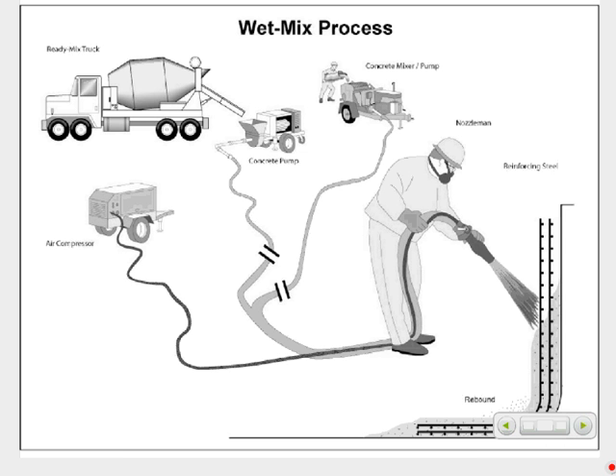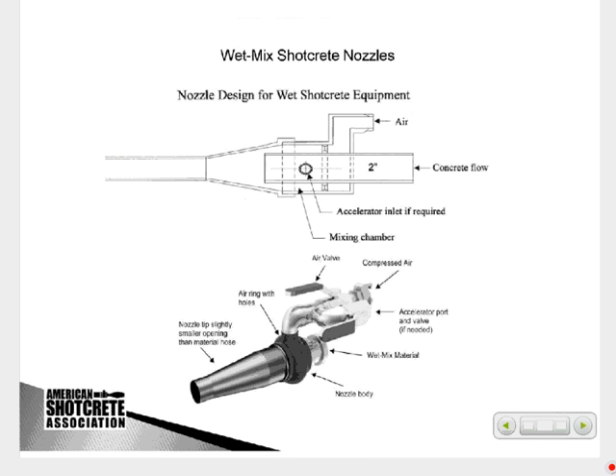It's often delivered in a concrete truck to the pump where it's then pushed with hydraulic cylinders. The swing tube type hydraulic pumps are the most common in wet mix. And then if you've ever seen a concrete pump in operation, you know you're not getting high velocity out the end of the hose. And that's why we have to introduce the air to help give it velocity. So the wet mix nozzle is similar to the dry mix. Basically here we have hydrated concrete coming from the right-hand side to the left, comes through the hose into the nozzle. We inject air, and that air pushes it through the nozzle and exits out at a high velocity.